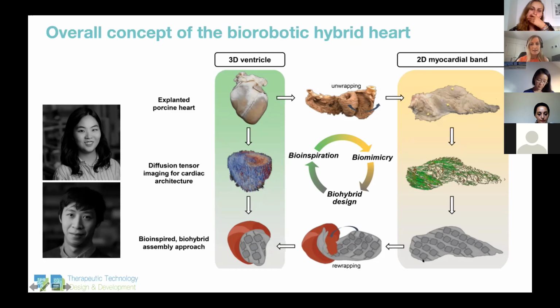Then we use soft robotic techniques to replicate that, and we orient these actuators, which are essentially small bladders embedded in a silicone matrix that we can pressurize, and that will contract in a predetermined fashion. So we have this soft robotic synthetic myocardial band. Meanwhile, we take away the real tissue from the ventricle, and when we rewrap around the dissected ventricle with this soft robotic band, we can integrate everything into one component. So we have organic tissue, apart from the myocardium of the left ventricle, or the muscle of the left ventricle, which we now replace with a synthetic soft robotic muscular structure that we can control and we can move, and which should move in the same way as the real ventricle.